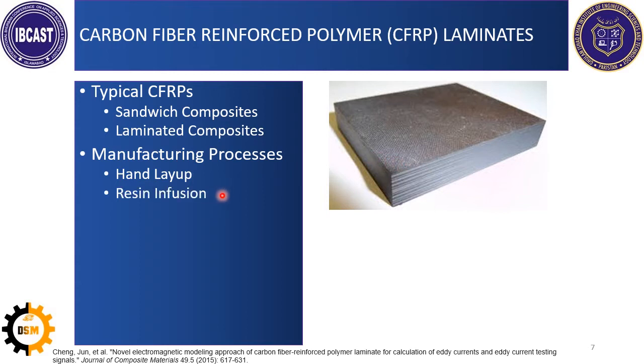The second is the resin infusion, in which you use a compressor to infuse the resin inside the carbon fibers using capillary action. There are some small tubes which suck the resin from one side and pull and push the resin from the other side, and all the resin is equally distributed in the laminate, and extra is extracted out through the catcher. So this is a better method than hand layup.